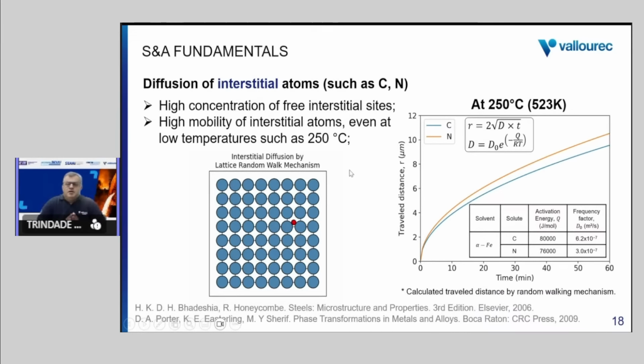And aging, so the product standard defined in their product specification. For example, if you take the DNV specification or API specification, they recommend to evaluate the aging of the material by using a temperature of 250 degrees Celsius for 1 hour. So you have to deform your material to the deformation grade that you want, and then after deformation, you need to submit your material to aging, which is 250, 1 hour.